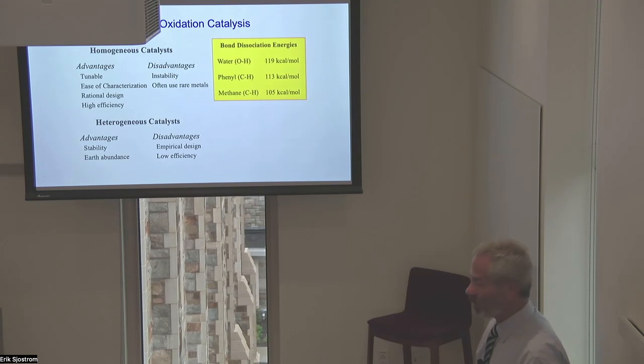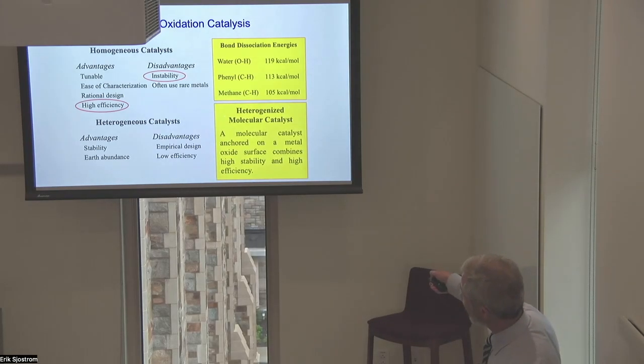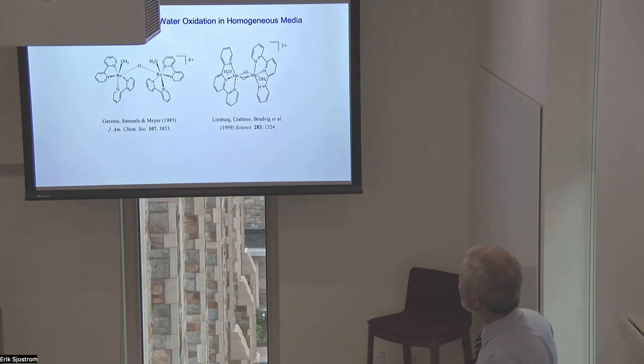How does it do it? It does it by keeping the catalyst away from others, buried in a protein and in a rigid environment, so it can't access these susceptible CH bonds. And that's what you can do by putting a molecule on a surface. If you heterogenize the molecular catalyst, it's now anchored, so it can't diffuse around and chew each other up. And you can combine high stability and high efficiency. And that's what we've been able to do with some of the molecular catalysts I'll describe.